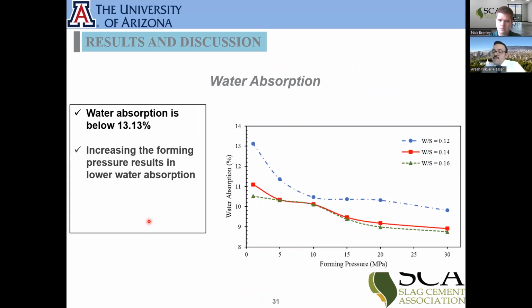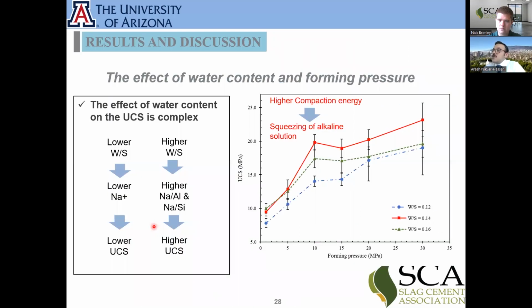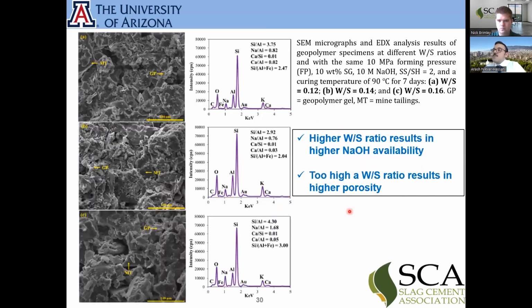Now from the results here, we decided to keep and try all of these samples for the water absorption, because we cannot decide just by this graph which one we are going to use. Even with high forming pressure, you're going to put more energy on this, and then probably the life cycle analysis is not going to work, and it's going to make issues. So we need to check all these samples for other critical criteria and see which number we should go for.